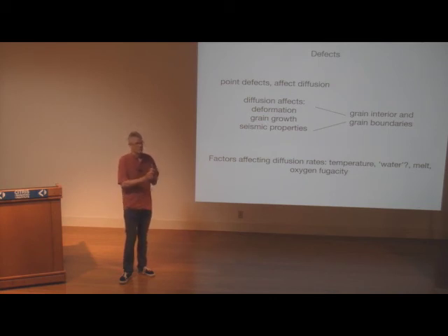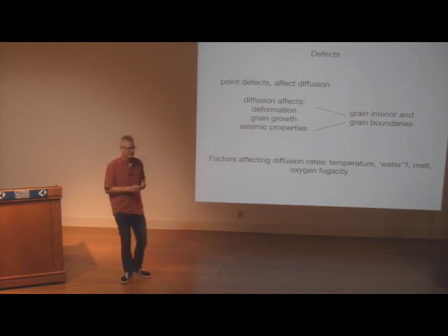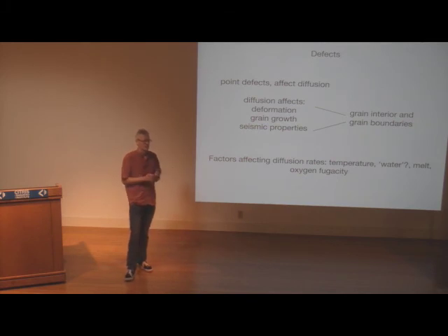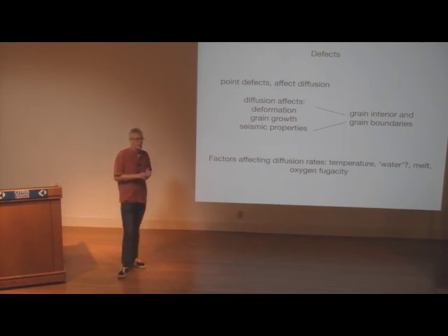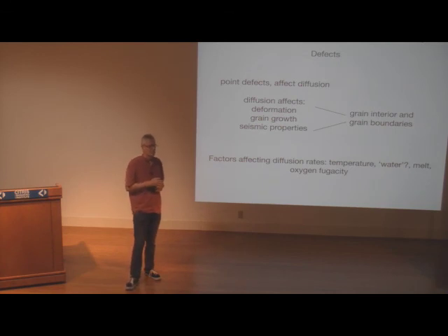For seismic anisotropy, you need a component at least of dislocation creep, right? So it can't all be diffusion creep. You have to have dislocation creep in order to get seismic anisotropy. So the grain size has to be large enough. If the mantle was very fine grained, you'd never transition into dislocation creep. So at this point, it's arm waving. Grain size is a very important parameter for all of these because it's so linked to diffusive processes, but the estimates are millimeter to centimeter.